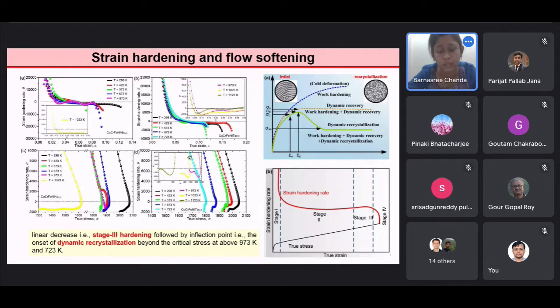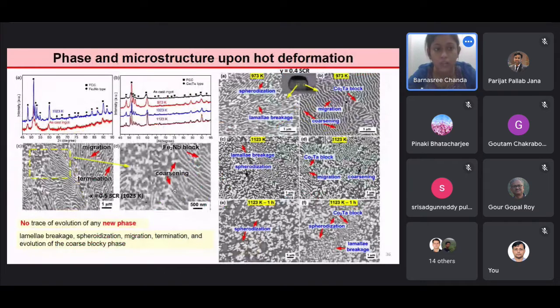the strain softening behavior. Thus, strain hardening rate versus true stress shows a steep decrease in theta with the true stress up to a plateau, which is the critical stress, beyond which dynamic softening is the dominating factor. Further, the phase and the microstructure upon hot deformation have been studied.